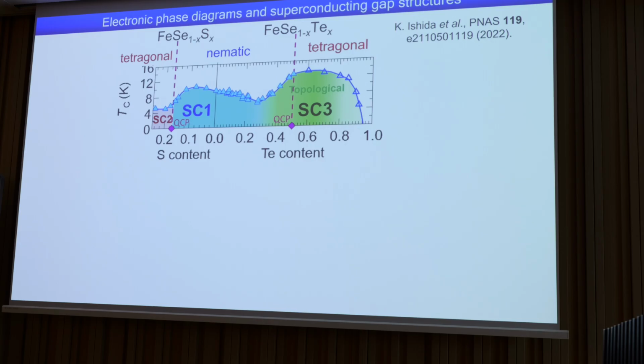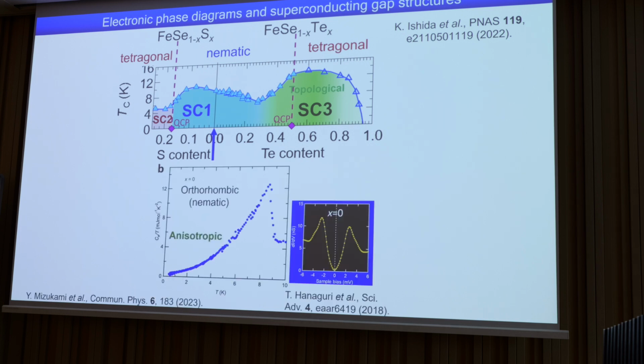Then, what about the superconducting gap structure? We can take a look at the specific heat data. This is the C over T as a function of temperature for iron selenium. You can see that the low temperature dependency is actually a T linear dependence.